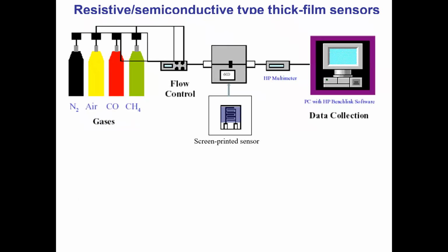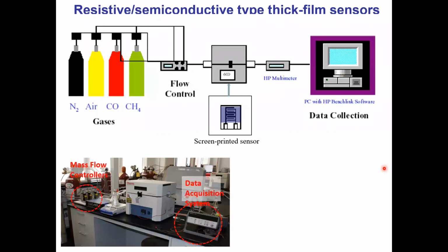So I'm going to talk about the sensor that is made by printing the film of the sensor on top of an interdigitated gold electrode that is printed on aluminum substrate. And we position this sensor inside a furnace where we can control the temperature of the furnace, and gas concentration can be controlled by mass flow control system by passing a single gas or mixture of gases. And then data can be collected by measuring with a multimeter and connected to a desktop for automatic data collection.